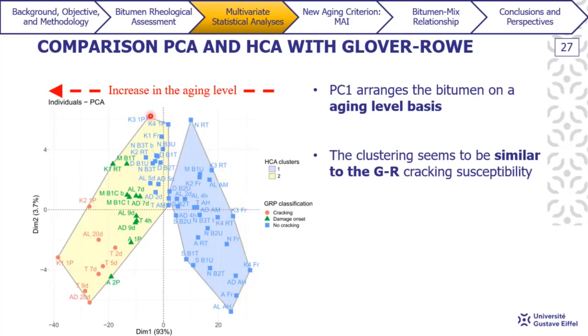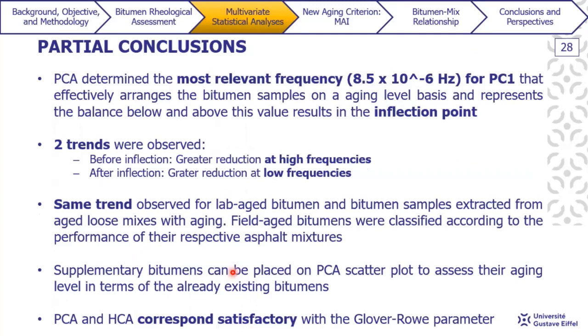In cluster two, we also have some blue markers here, but we can also see the green one represent bitumens that are on damage onset according to the Glover-Rowe parameters, and the red one represent bitumens that already display an increased cracking propensity. So what we observed, well, with PCA and HCA combined, was that PC1 managed to arrange the bitumen on an age level basis. And the clustering seems to be similar to the Glover-Rowe cracking classification. So here are some partial conclusions.